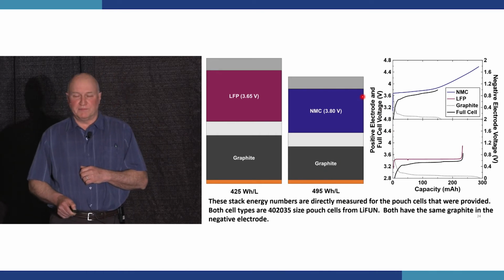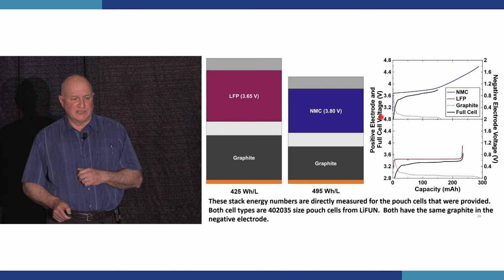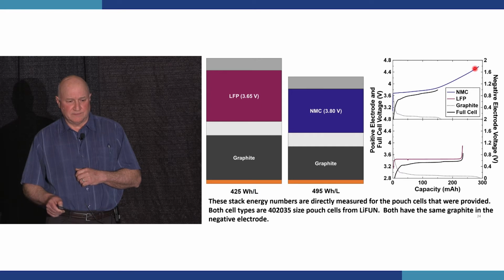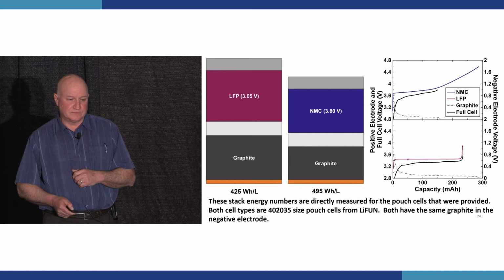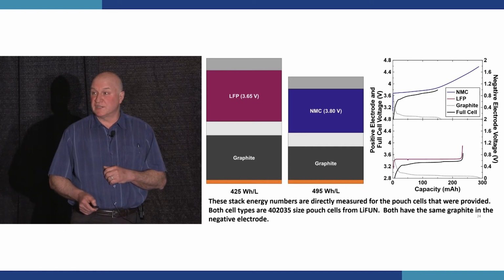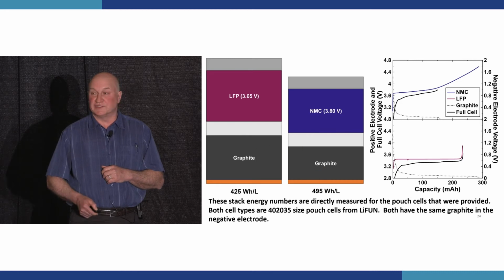And what we mean by balanced to 3.8 volts is if you take a look at the positive electrode voltage versus capacity curve and the negative electrode in the dashed line and the full cell curve in black, when the full cell reaches 3.8 volts, the graphite is full. Okay, so that's what we mean by balanced to 3.8 volts. Now, both of these cells that we're going to compare have exactly the same graphite in the cell.